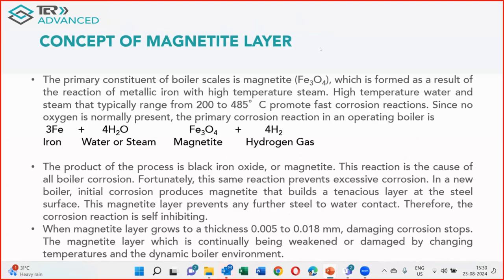Now, the other aspect which I wanted to highlight in this talk is the concept of magnetite layer. We all know that in hot water above 80 or 100 degrees, when it comes in contact with iron or steam, it forms the magnetite layer, that is Fe3O4, and it liberates hydrogen. Basically, it's a corrosion reaction which occurs for a very brief period of time, where this magnetite layer further protects against corrosion. Now, this magnetite layer, it is important to understand.